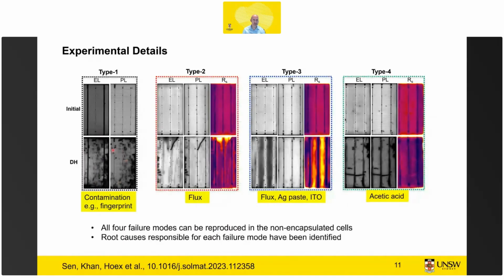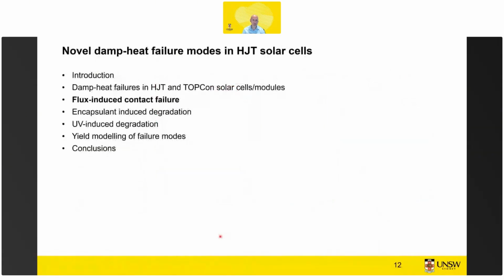So we identified that this type 1 failure is contamination. There's various root causes for this, but if you see this in the factory, you can focus on contamination sources. Then soldering flux, and I will go into a lot more detail on how that can cause degradation. And then for heterojunction, we saw that the soldering flux can react with both the paste, so the silver paste, and the TCO, that in this case was ITO, so indium tin oxide. And acetic acid in combination with soldering flux leads to this busbar darkening. And that's what we only see when we have EVA modules. The cell level testing can be done very rapidly, which allows us to make rapid progress.